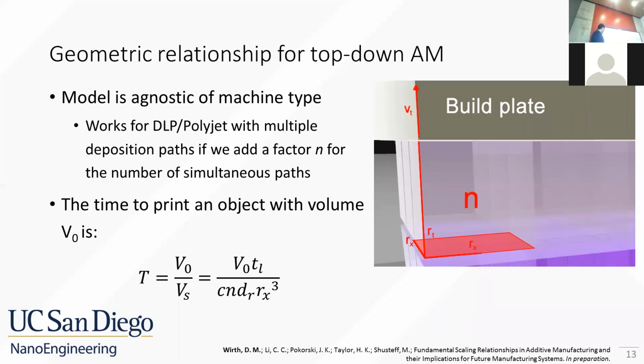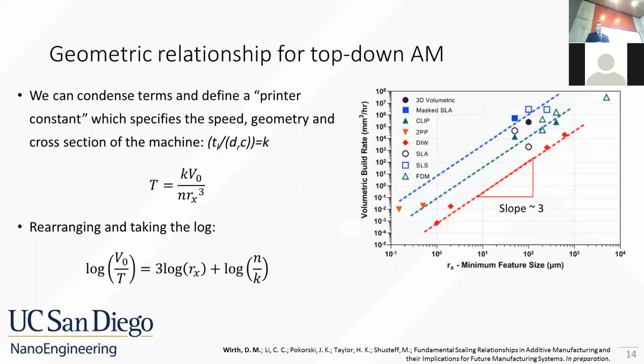And so using this, we can come up with a relationship for the volume or the time to print an object with a known volume, which is related to the volume of the object, the resolution you're producing at, and these known geometric constants. Rearranging this relationship and taking the log of both sides, we can come up with a relationship in the form of y equals mx plus b.